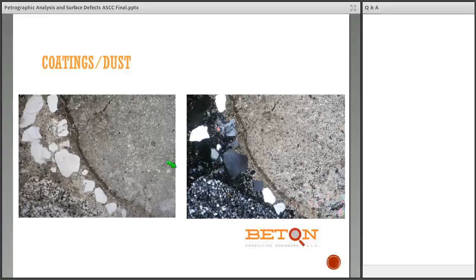Coatings and dust. This is in plane polarized light and thin section. You can see this is a coarse aggregate particle paste interface, this whole thing being a rather large coarse aggregate particle. But when you put it under cross-polarized light, you can see there's a little micro crack that runs right along that boundary, and then you can see a lot of dust that is adhering to that aggregate. In this instance, it might indicate that you have a lessened paste aggregate bond due to the dust coating on the aggregate.